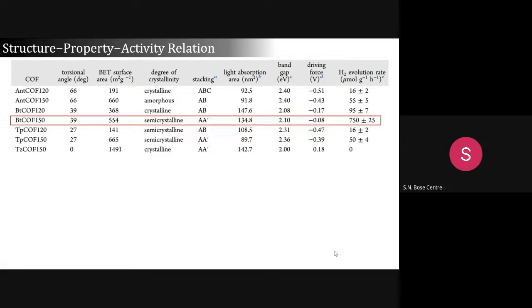These are the 120 and 150. You can see the torsional angle presented here. This is the porosity. The BtCOF has only 550 meter square per gram porosity, whereas the TzCOF has 1490. But it doesn't have sufficient driving force. That's why it could not do the photocatalysis. The TpCOF has 600, but still it is lower than this one. Then we have to look at the other parameter. So what is that parameter?